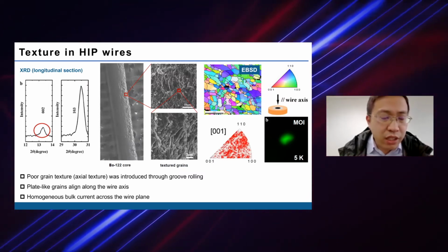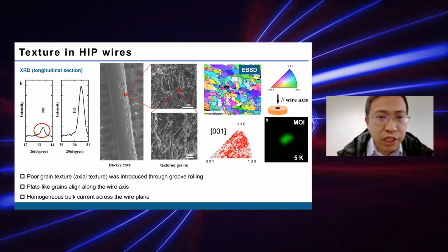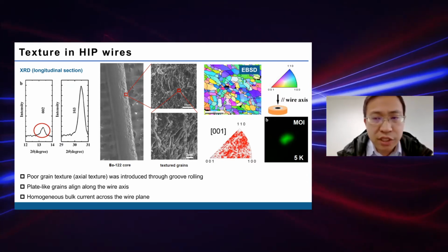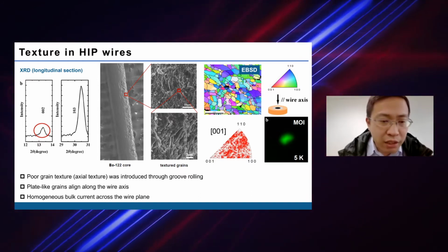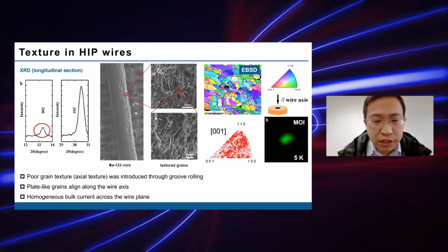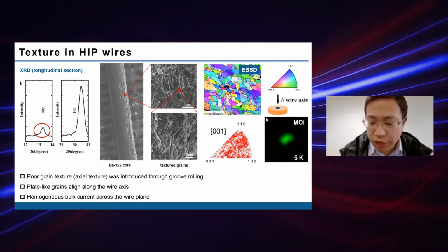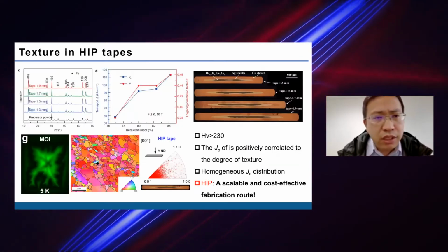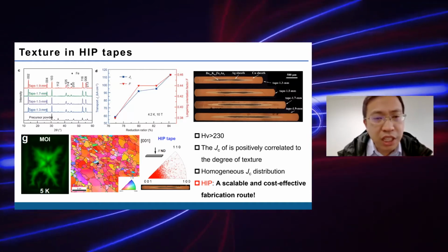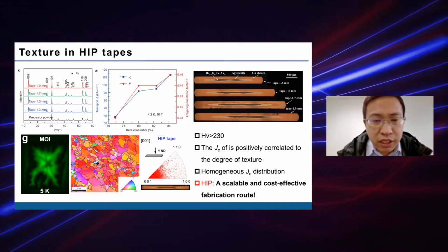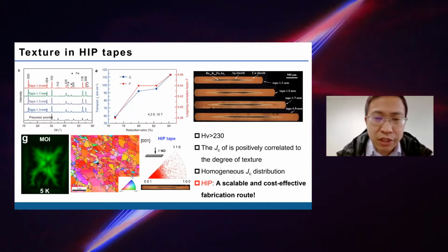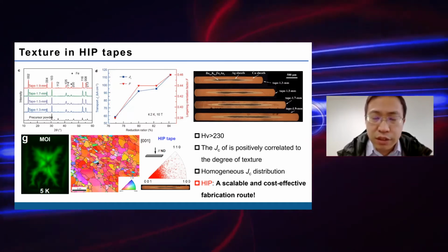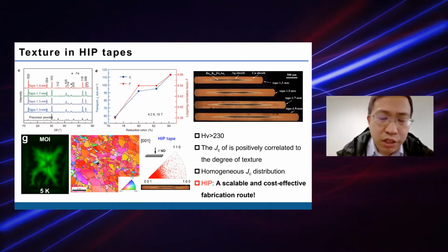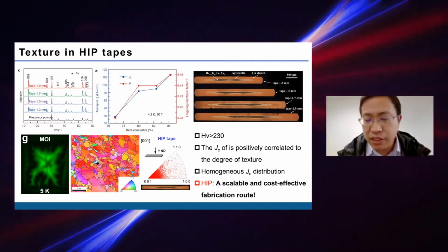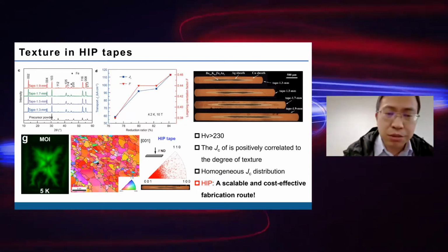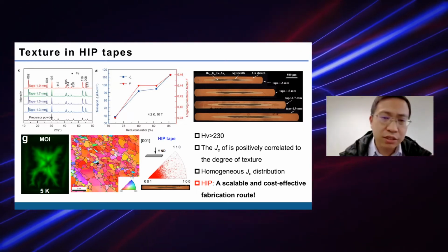Actually, we can only get poor grain texture in the HIP wires, as evidenced by the XRD and EBSD measurements. Although the plate-like grains align along the wire axis, we can get a homogeneous transport current across the wire plane. On the contrary, the c-axis texture is largely increased in the HIP tapes. And with the increasing reduction ratio, we can simultaneously get an increased c-axis texture and increased transport current density. So the HIP process is a scalable and cost-effective fabrication route to produce long wires and tapes.